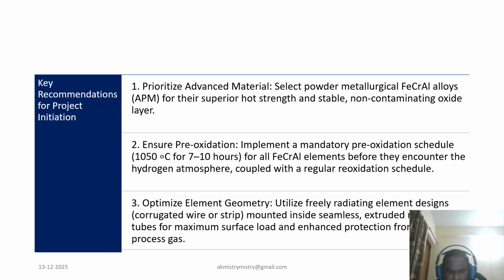Secondly, we have to ensure the pre-oxidation. Implement the mandatory pre-oxidation schedule that we have already discussed, that is, this is to be performed in air for 7 to 10 hours before installation and use for all ferrochrome aluminum elements. Third is to optimize the element geometry. Utilize freely radiating element designs, ideally mounted inside the seamless extruded radiant tube for maximum protection. At the same time, we also need to see that this hydrogen gas should be free from contamination by nitrogen, carbon monoxide, carbon dioxide and moisture.